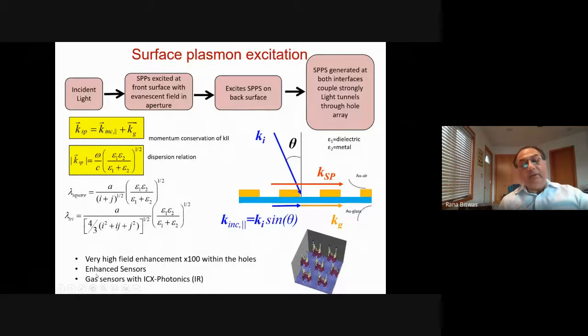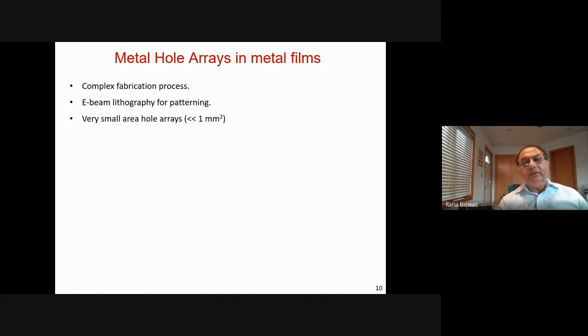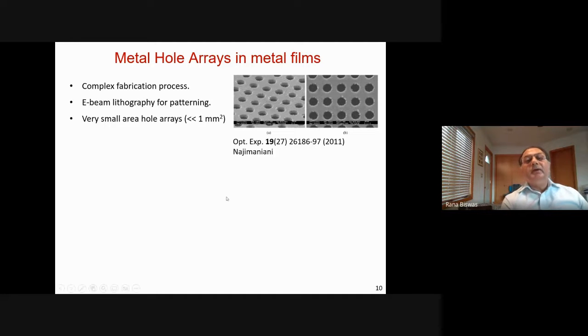And for many years, I worked with this company, ICX Photonics, and we developed high sensitivity gas sensors using the infrared properties of these hole arrays. So the first thing you want to note here is that to make a hole array is a very complex fabrication process. And in the early days, most people used e-beam lithography for the patterning. And this resulted in very small hole arrays, less than 1 square millimeter.